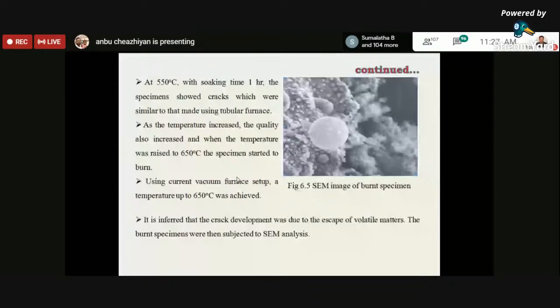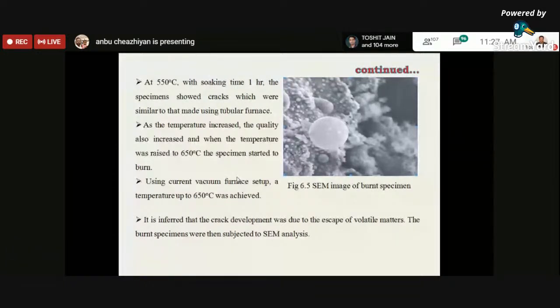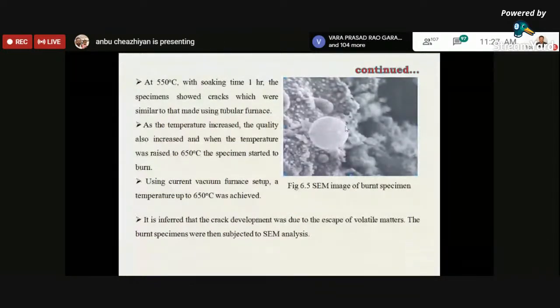The only thing is we can increase the sintering temperature. In fact, the crack development was due to the escape of volatile matter, but the specimen was subjected to SEM analysis. Here we can see that the nanoparticles appear. It is not burnt. Due to the escape of volatile matter, it gets oxidized, so we can't get the composite. That is what we observed from that research.